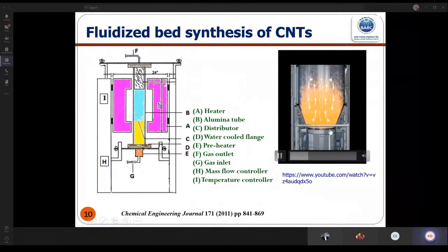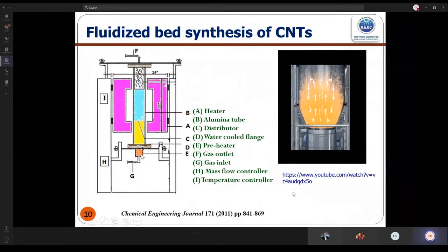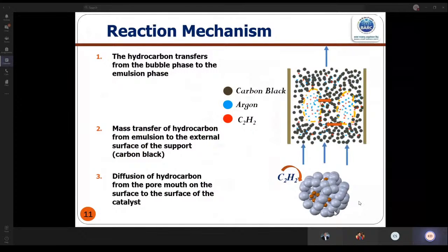If we pass the gas, these carbon black particles will start to circulate in this fashion, and from the bottom we will send the ferrocene with the carrier gas. At high temperature they will pyrolyze and give the iron nanoparticles, and then the hydrocarbon comes. I'll give the mechanism which we developed, the mechanism which was published.